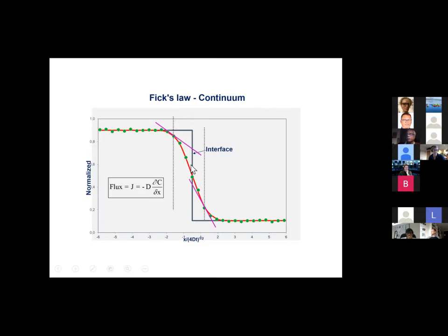So that's a trick that we gloss over when we teach this kind of concentration profile and Fick's law, that Fick's law actually does not apply right at the very beginning. Because if you put in an undefined large concentration gradient, your flux would be infinite or something, and you'd homogenize everything in one go. But it's not even infinite, actually. It's really undefined at this point here. It's a singularity. So how do you deal with that?